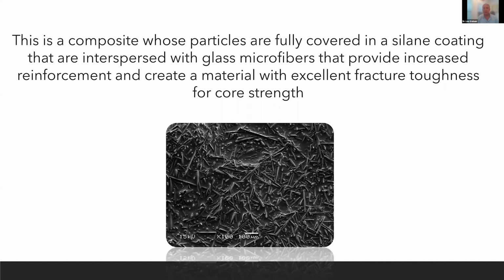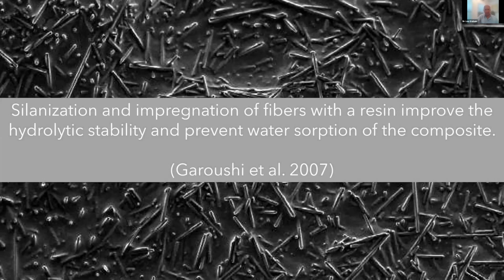So in this picture, you can see the randomized particles, the way they're lined up. They're random. They're all coated with a silane, and they're all interspersed amongst the resin composite. And all they're going to do, well, I won't say all they're going to do, but what they're going to do is provide an excellent fracture toughness for the core. So silanization and impregnation of these fibers with a resin improve the hydrolytic stability and prevent water absorption of the composite, as studied over 15 years ago by Garoushi. So this is nothing new, well studied, and this is the formulation that is in Everex Flow.